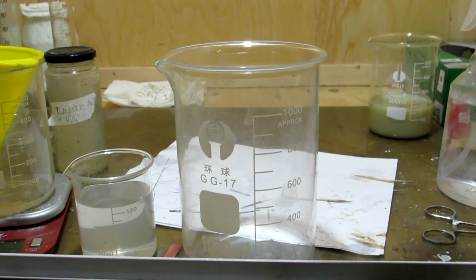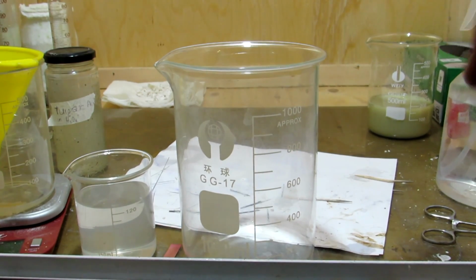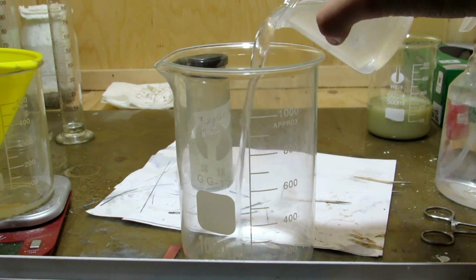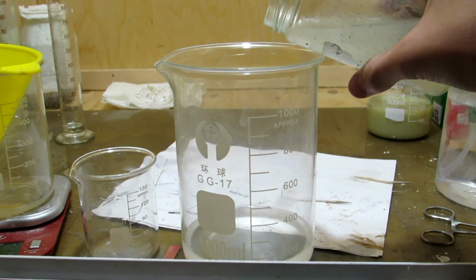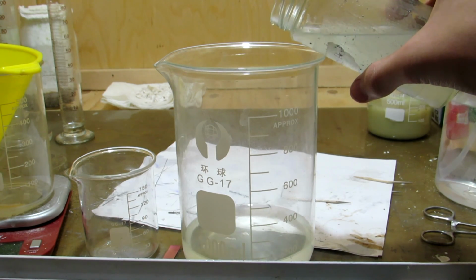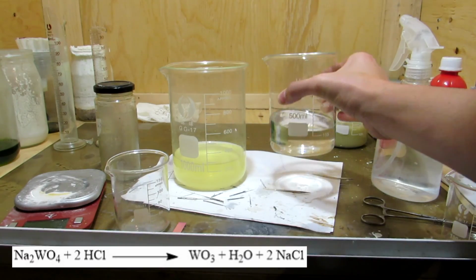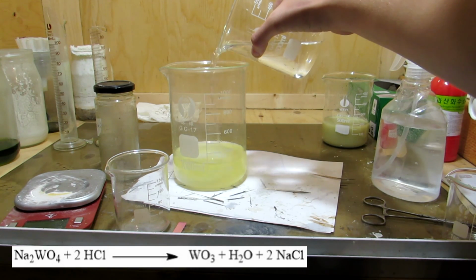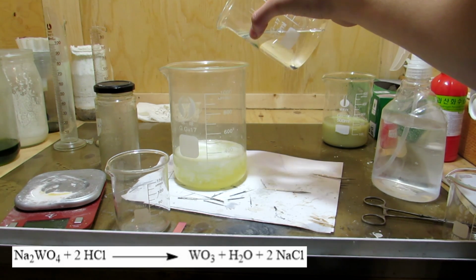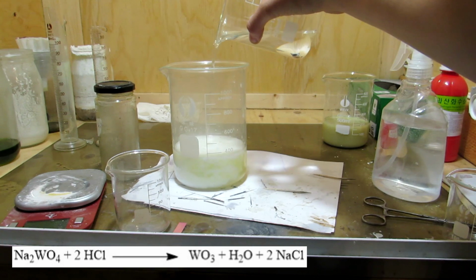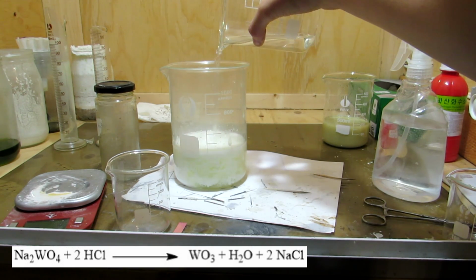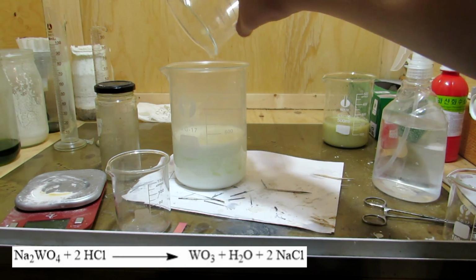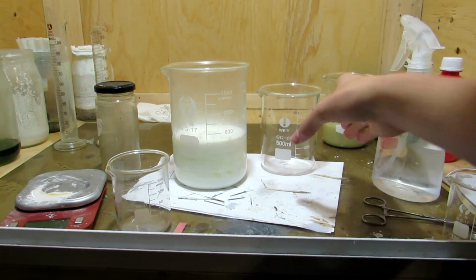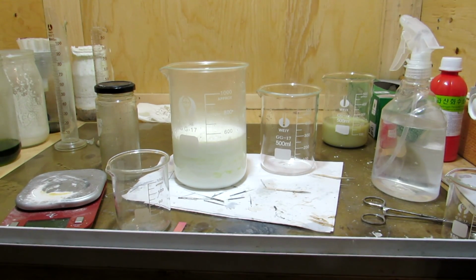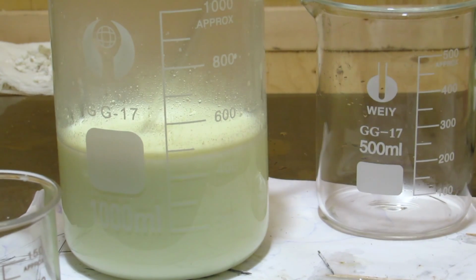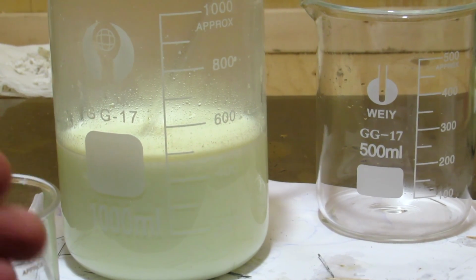While that is dissolving, we can convert the sodium tungstate and tungstic acid to tungsten trioxide. First, the tungstic acid solution is added to the sodium tungstate, and excess sodium hydroxide will react to form more sodium tungstate. Next, we can add about 200 milliliters of concentrated hydrochloric acid to convert the sodium tungstate to tungstic acid, which precipitates out. Concentrated hydrochloric acid can be purchased from hardware stores as muriatic acid. Interestingly, the precipitate was initially white, even though tungstic acid is yellow. However, after mixing the solution, it took on a light canary yellow color.